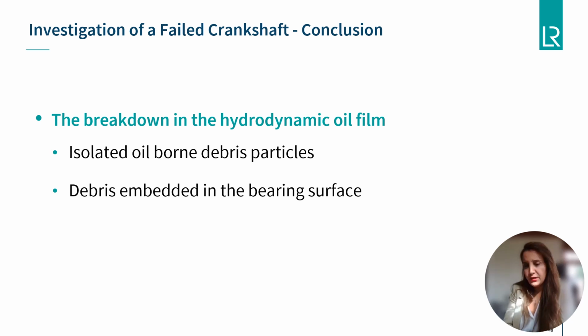Typically, the hydrodynamic oil film in bearings can vary between 2 microns and 20 microns thickness, dependent on pressure, viscosity, and crankshaft dynamics. Thus, for thin oil films, it does not require a significant amount of or large debris particles to generate disruption in the oil film.